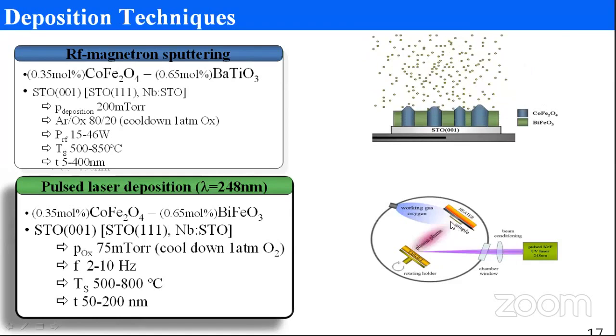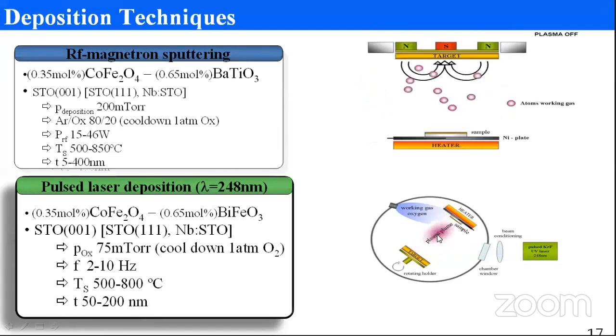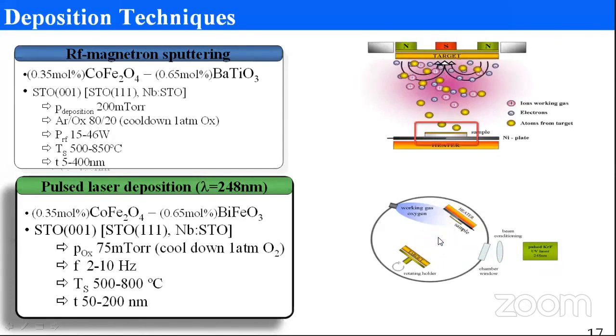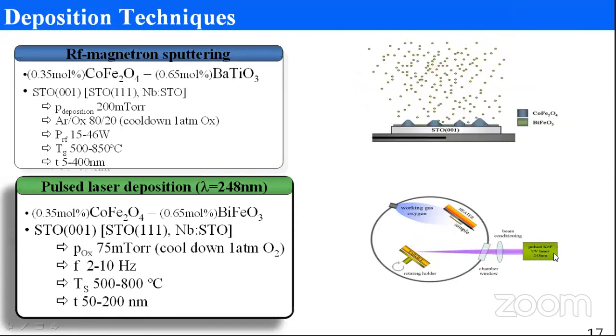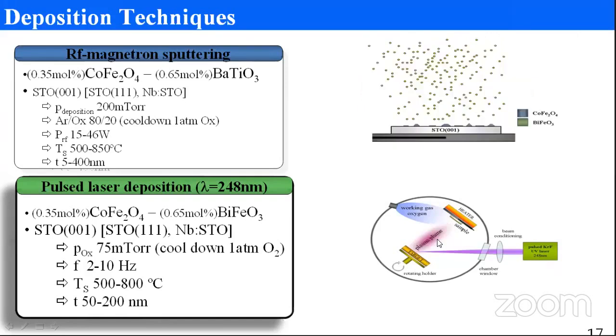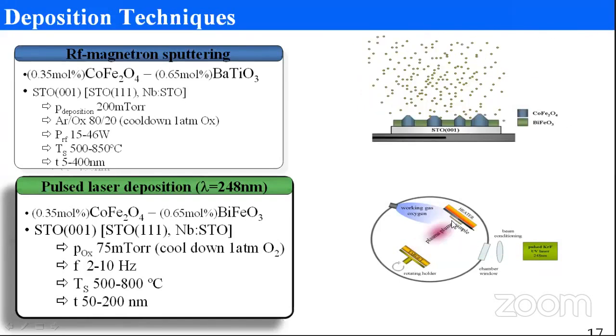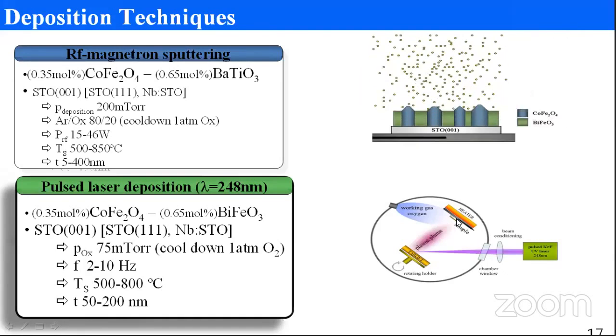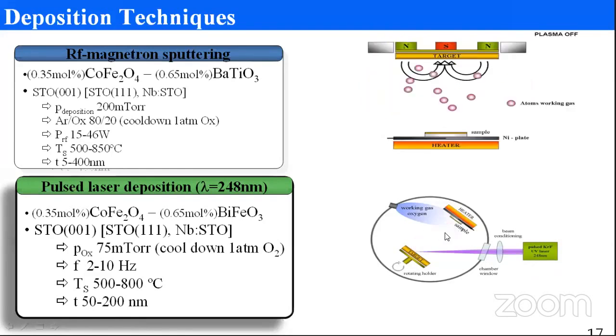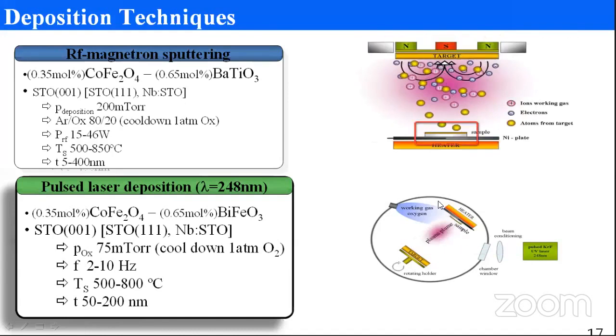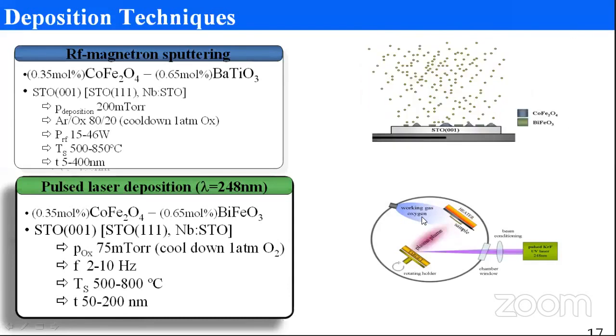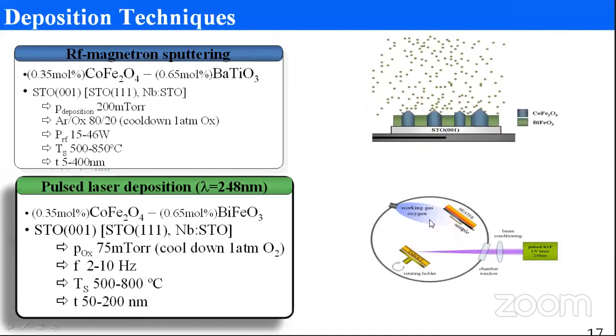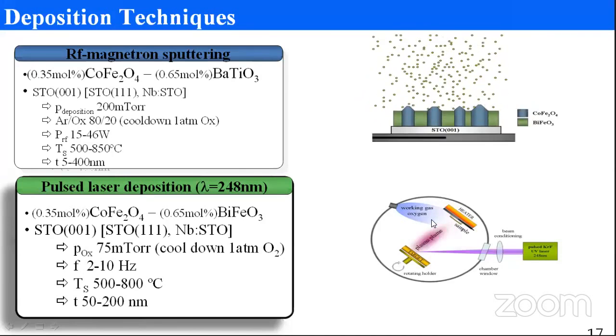Okay, this is a simple cartoon which shows how thin films are produced in pulsed laser deposition. You have a krypton fluoride excimer laser where the pulses fall on the target. If you put the substrate on a heater, you can change the temperature and grow at different temperatures, and you can produce epitaxial films. You can also maintain the environment. If you are working on oxides, you can maintain oxygen, or if you are working on metals, you can work with argon or nitrogen, so that you can produce highly epitaxial and highly pure materials.